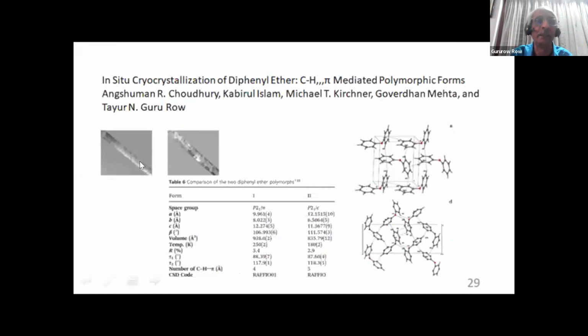last but one, where we actually took a liquid. This is an example of diphenyl ether where we crystallized the compound in a capillary in situ on the diffractometer. And the way in which the crystallization was processed, one is a rapid cooling from room temperature to very low temperatures, and repeated rapid cooling and heating generated one type of crystal. And then the other one was a slow cooling rate, and that slow cooling rate resulted in a different crystal structure. So we could generate the polymorphic forms, alpha and beta, as we call them here, 1 and 2.